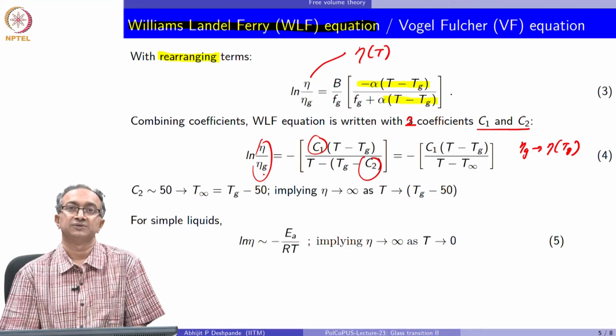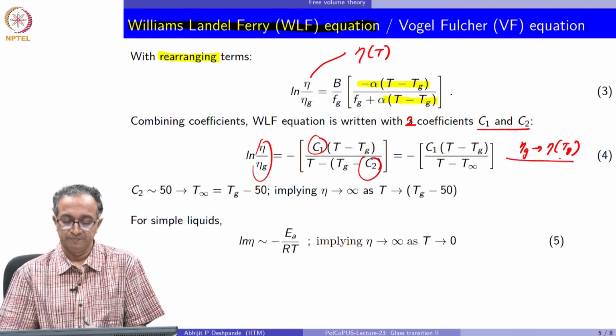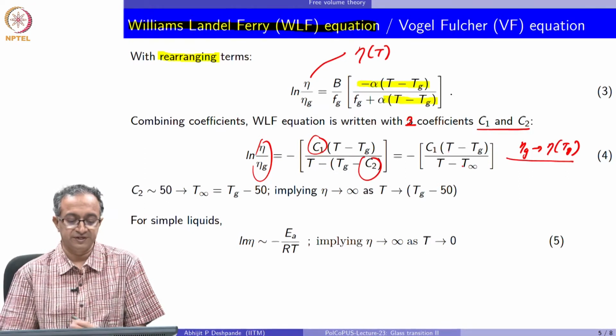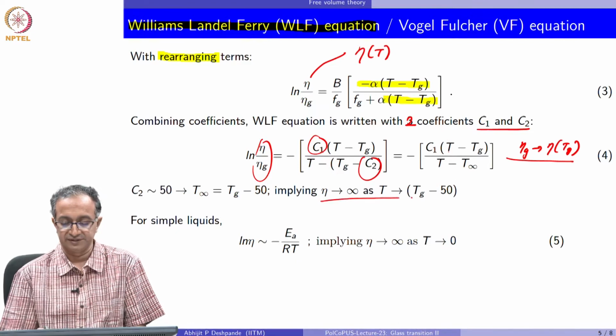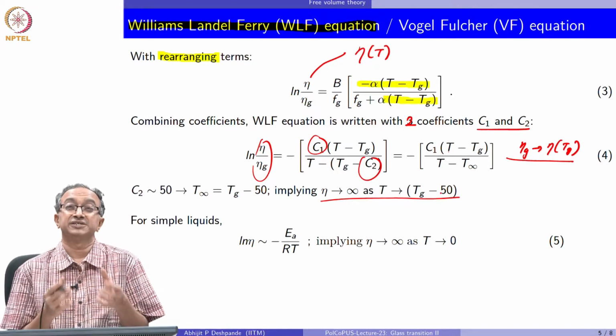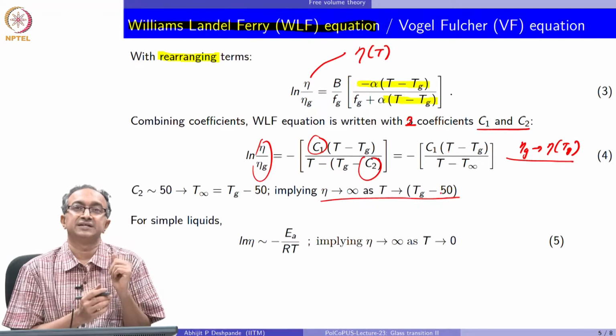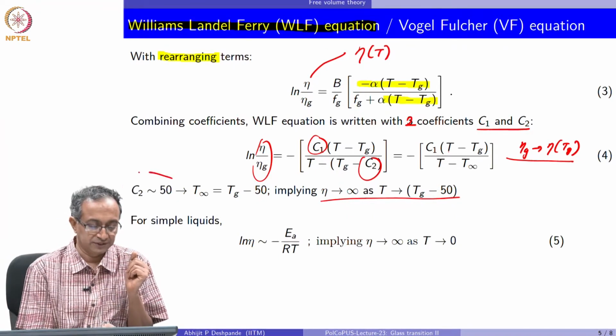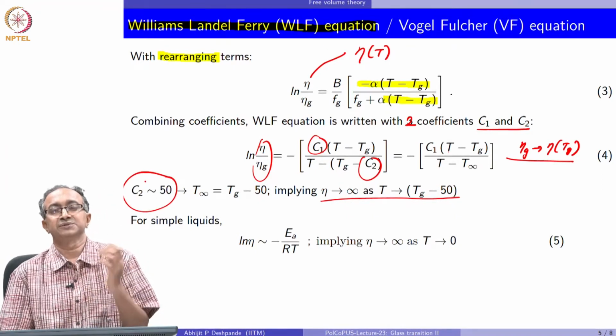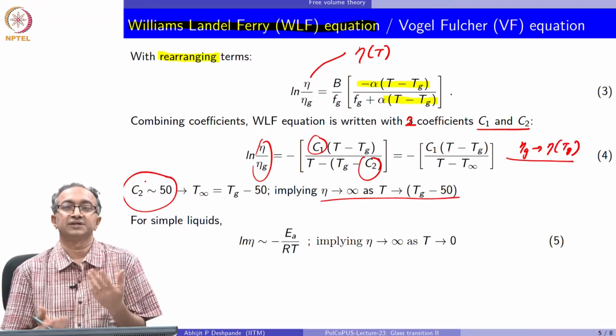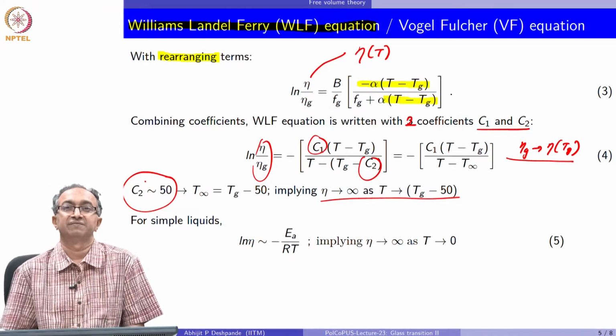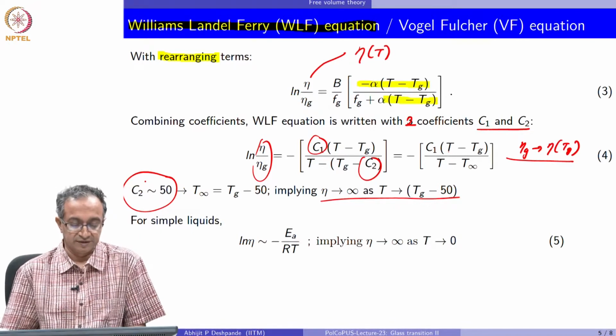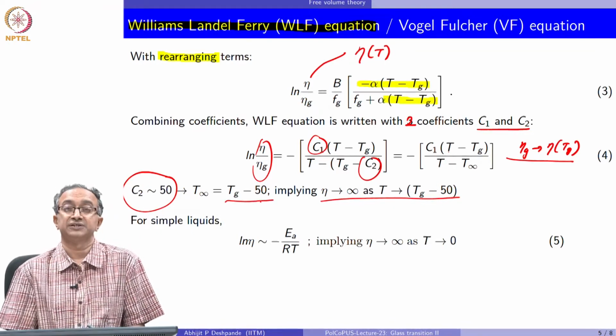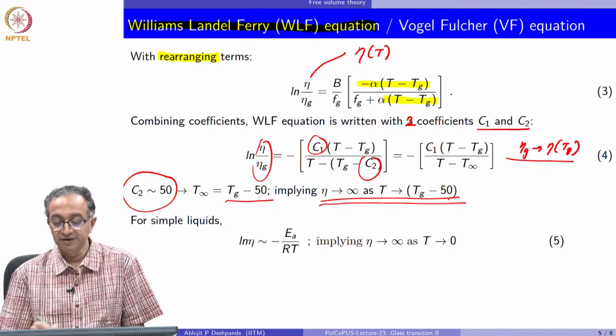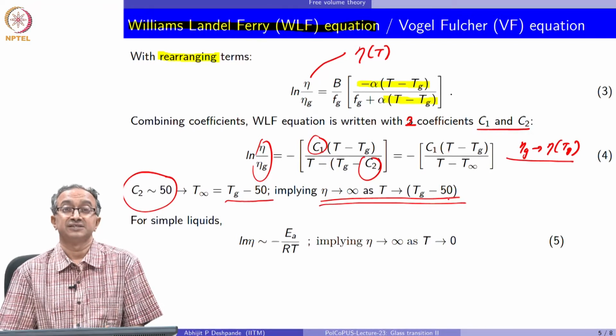One key thing you can observe is if T is equal to Tg, then eta will be equal to eta g, which is by definition, and if T is equal to T infinity, then eta becomes infinite. So, at this fictitious temperature which is around 50 degrees Celsius below glass transition, because for many of the polymeric systems C2 is around 35, 40, 50, 55, it is a temperature below the glass transition temperature, basically segmental mobility completely ceases, and therefore, viscosity becomes infinite.